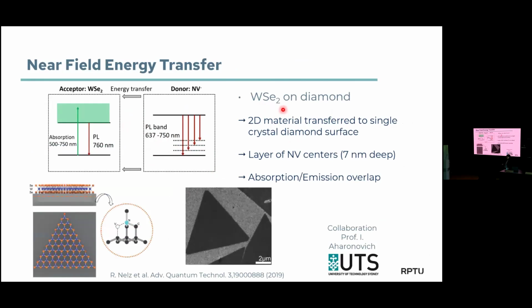In this case, we had a 2D material, not the graphene, but a luminescent 2D material. In this case, it's tungsten diselenide. We also have molybdenum disulfide now. In a nutshell, you can grow this material really as a single atomic layer, and they are fluorescent. They have an excitonic luminescence. And in this case, it was the group of Igor Aharonovich in Sydney. They transferred this material, the tungsten diselenide, to one of our diamonds.